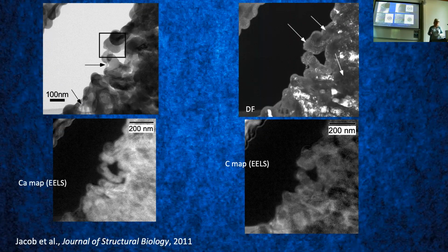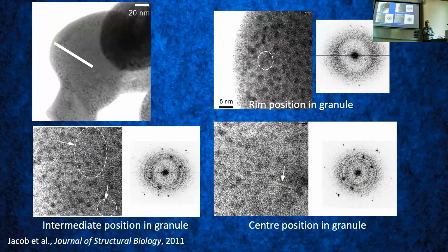And what we did then is we did electron diffraction across one of these granules to see if it's actually crystalline or not. So we chose this one here, which showed up as amorphous, and I've indicated the traverse that we did here. So at the rim position, we got a diffractogram which shows us it is actually mostly amorphous. We have an area here where we did find a little bit of crystallinity, but a little bit is fine. Still, the majority is amorphous.